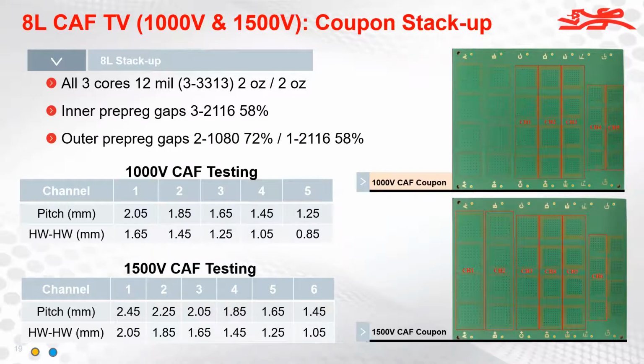And so with this product, IS550, there have been multiple CAF test vehicles, and there have been several applications at both 1,000 and 1,500 volts where we've tested the material, like this example here, and looked at the thickness between the biased pairs of conductors in the board. And so this material actually behaves very well. And we see hole wall capability is also improved by this resin system.